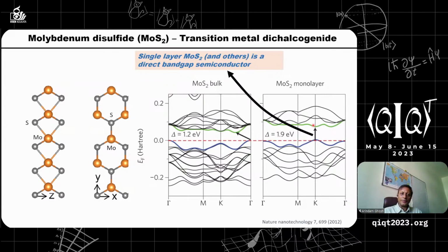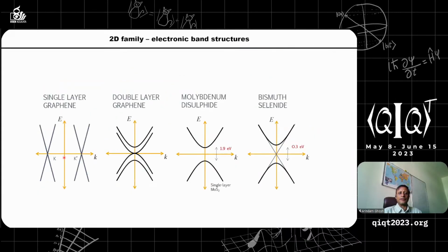Now, overall, these two-dimensional materials can have a huge number of different possibilities of electronic band structure. In the case of graphene, you have seen this conical band structure. If you use bilayer graphene, there are two graphene layers on top of each other, then the two layers interact with each other, and that interaction immediately changes the band structure, and it now becomes parabolic, like a standard semiconductor, but without a gap. But then you come to molybdenum disulfide type of structures, where you now have a semiconductor-like, beautiful parabolic band structure with a band gap.